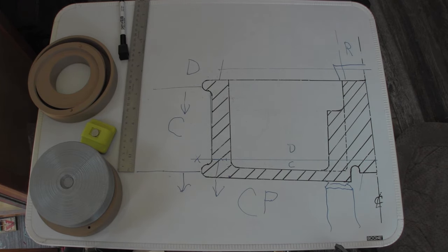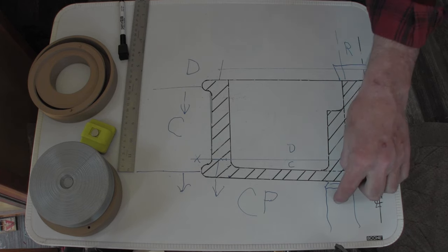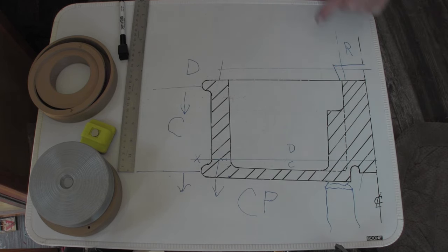And the nice part about that is, depending on the size of the riser, you either cut it off because you got a nice witness line there, or if it's small enough and you got enough room to do it, you can smack it with a sledgehammer and break it off. That would be up to the foundry how they want to do it, but that would give you enough riser material, two of those, one on each side where this added boss or lug was. So those are different ways you could build it.